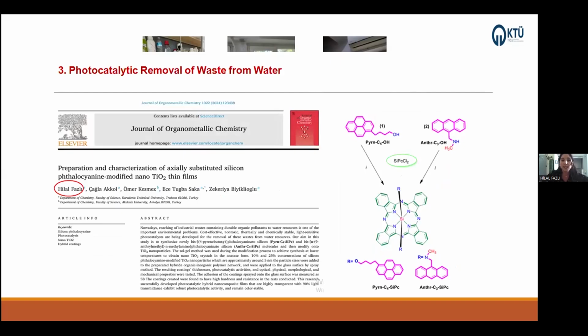In this study, a silicon disubstituted phthalocyanine molecule was synthesized and subsequently modified with titanium dioxide to produce nanoparticles. The synthesized nanoparticles were applied for the removal of methylene blue, commonly considered a pollutant. It was determined that the silicon phthalocyanine molecules exhibit high photocatalytic efficiency in degrading methylene blue.